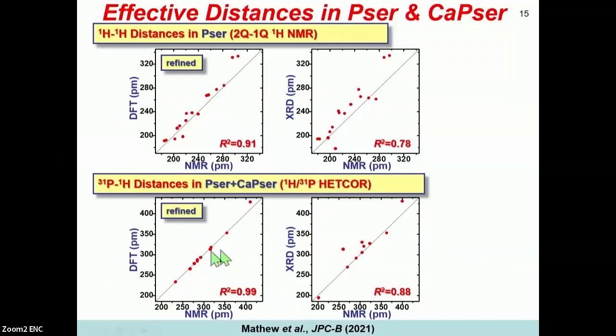In the plots below here, you see phosphorus-proton heteronuclear distances, now also including the calcium salt of phosphoserine. And these were obtained by HETCOR. In both cases, as you can see, the DFT refinement gives a better structure, so to say.